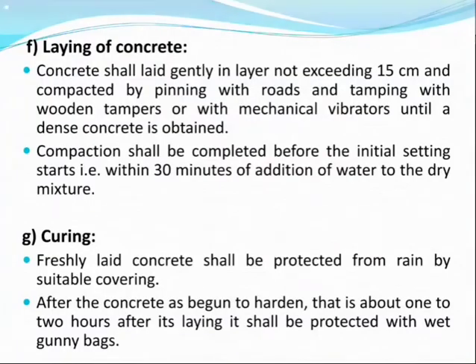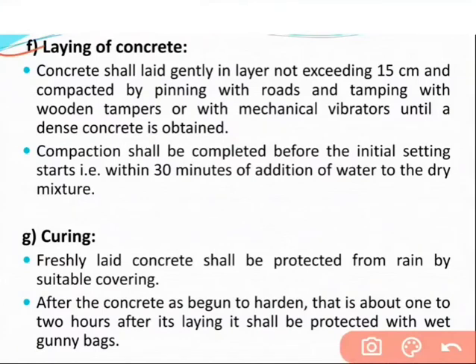Now next is the laying of concrete. The concrete shall be laid in layers not exceeding 15 centimeter and compacted by pinning with a rod and tamping with a wooden tamper or with a mechanical vibrator until a dense concrete is obtained. Compaction shall be completed before the initial setting time starts, within 30 minutes of addition of water to the dry mixture. Over vibration, which will separate coarse aggregate from concrete, should be avoided.